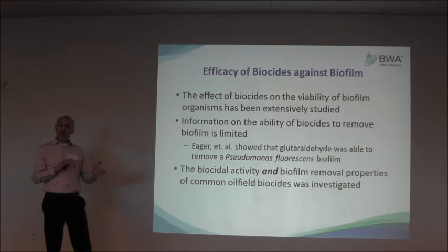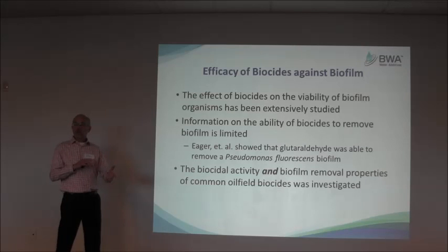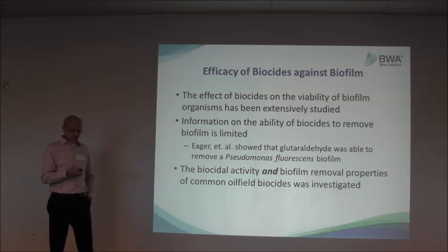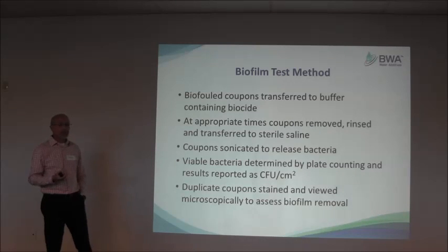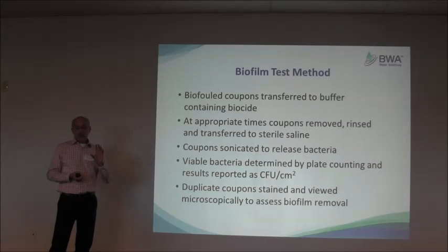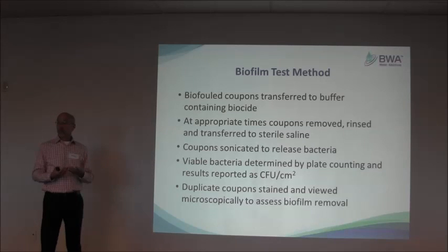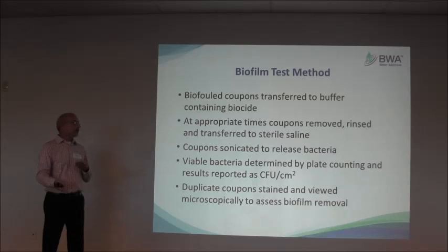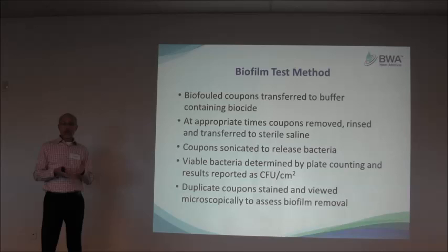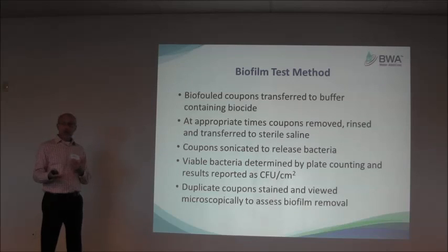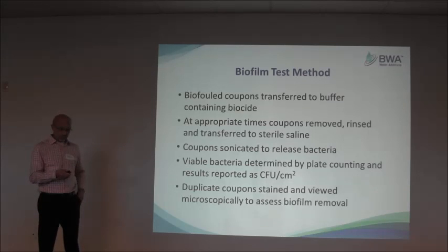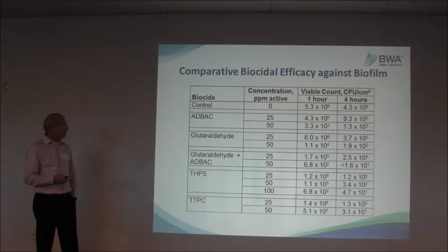What we've done is look at both aspects of biofilm control: killing the microorganisms while they're on the surface, and also looking at the ability of products to remove those organisms from the surface. We use metal coupons and allow a biofilm to form on them. We then expose those coupons to different biocides at different concentrations for different lengths of time, and then test the coupons for the level of viable organisms remaining. We also have a duplicate coupon that we stain and look at under a microscope.